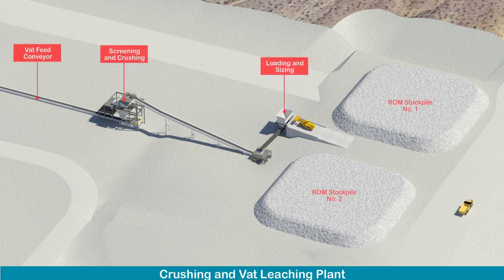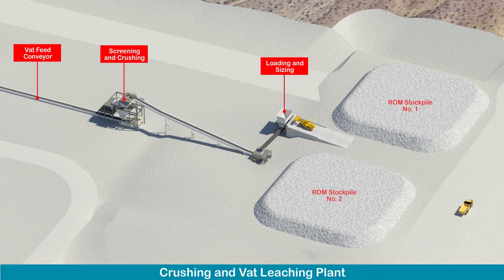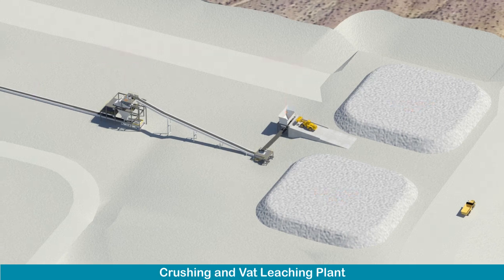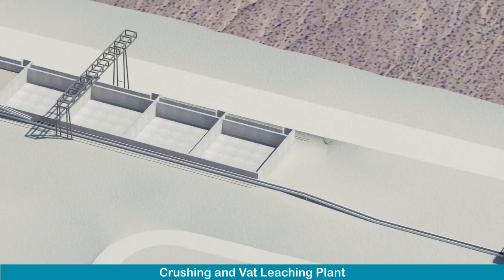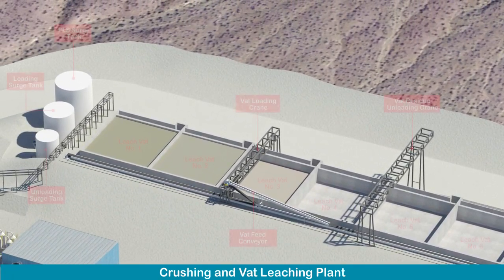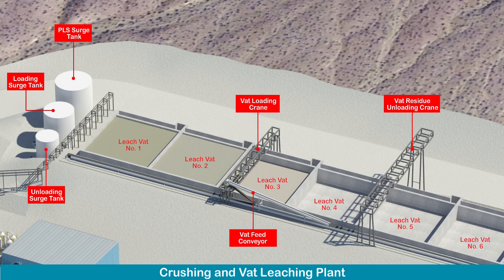Stockpiled ore will be crushed and sized to reduce the rock particles to no more than 1 inch or 25 millimeters diameter. The sized ore will be loaded into a series of large concrete vats by conveyor. As the ore is being loaded, the vats will be flooded with an acid-water mix and the leach process will begin. After 4 days in the vat, virtually all the lithium and boron will be leached from the rock into the acid solution. The lithium-boron-bearing solution is referred to as pregnant leach solution, or PLS. The vats are unloaded and the vat leach residue, or spent ore, is moved to an adjacent dry stack storage facility. This process means there is no need for a tailings dam.